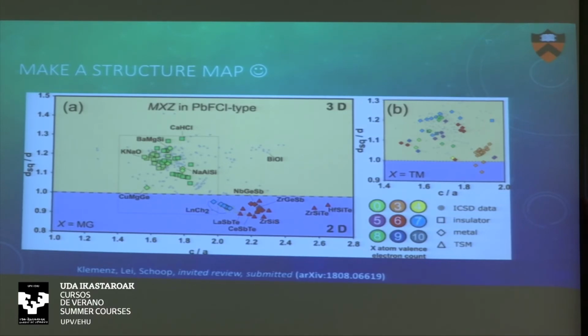All the green ones are the ones where we trusted the Materials Project enough to look up the electronic structures, and the gray ones are the ones where we think the data there is not reliable. The shape of the points indicates the property, and the color indicates the electron count. So all the green points here are charge balanced, and they have 0 or 8 electrons, and mostly all of them are insulating. The few metallic examples are just because they're semi-metals, like we said, with 2 overlapping shells like in mercury telluride. And in all these, the crystal structure indicates that the square net is not isolated.